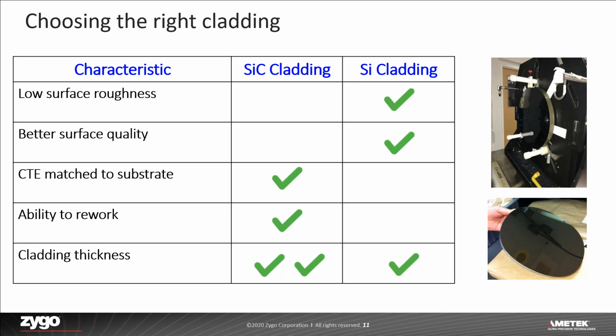In choosing the right cladding, before we jump in and talk about the cladding, I want to mention that the pre-clad surface quality is a very important consideration. Substrate flatness concerns and subsurface damage of the pre-clad mirror face can lead to extra optical fabrication down the line. I want to talk about the two most common claddings we see, CVD silicon carbide versus silicon. This is very common. We have these conversations with customers frequently.